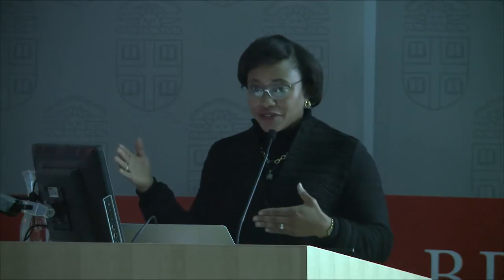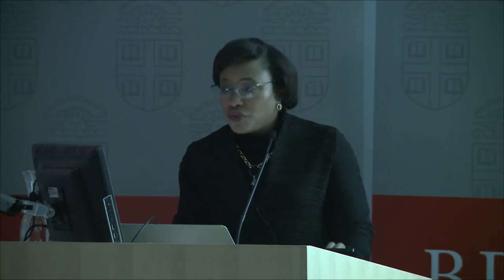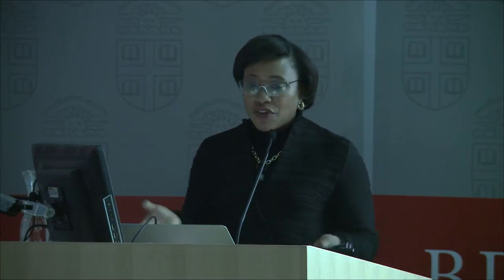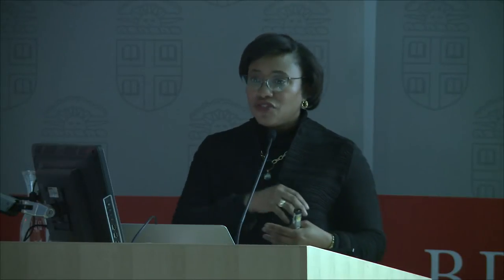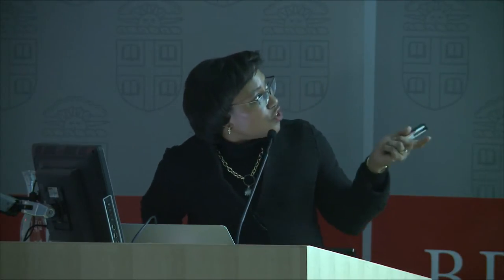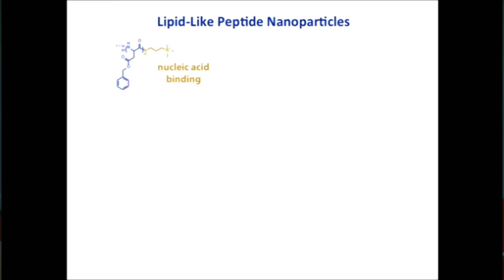And siRNA has been of interest in the field of medicine for quite some time because you can actually address many diseases by turning off errant genes that are essentially allowing cancer cells to survive, influencing disease in other ways. Now, it turns out that all genetic material, nucleic acids, RNA, DNA, are negatively charged. And if we want to deliver them, we need to use methods which allow us to encapsulate these negatively charged species and get them into the cell cytoplasm where they can do all of their work. So we're using nucleic acid binding as an approach in which we can use this very charged region at the end of this polypeptide. So we're making our same polypeptide that you saw before, but we're adding this quaternary ammonium salt so that we can get nucleic acid binding.